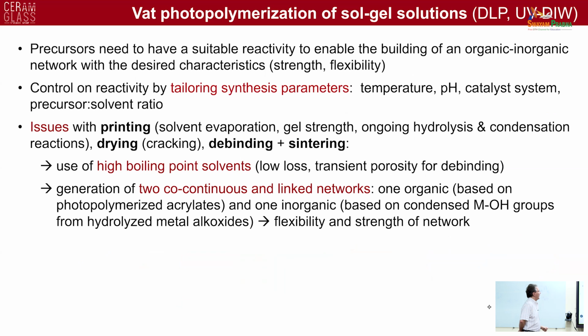There are also a lot of issues with this approach. First of all, you need to have a precursor that has suitable reactivity to enable the building of an organic-inorganic network with the desired characteristics. So shaping the liquid is not enough. The part needs to be handled. So you need a certain strength, a certain flexibility of the part.